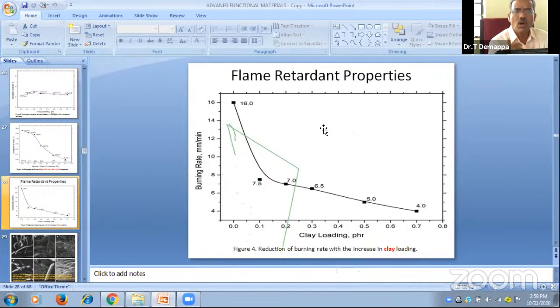The char does not allow the combustible gases to contact our material. So there is no contact between the combustible gases, including oxygen, and our composite material. So it retards the combustion. And another one is that it acts as a laminate barrier, a barrier to the propagation of fire. So these are the factors. It reduces the burning in the burning test.